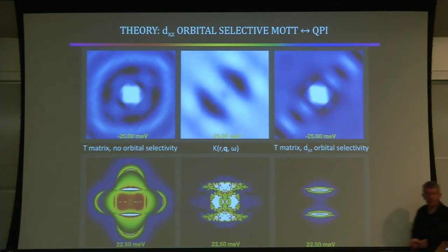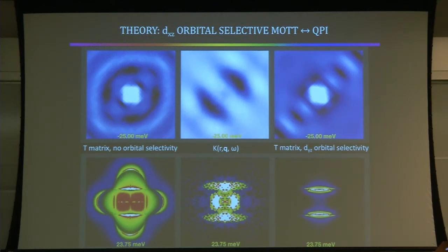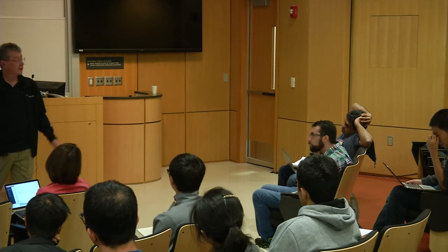So if you assume the impurity scatter... Say again? So the model for the impurities? It's a delta function in real space, so it's homogeneous in K space. The T matrix doesn't have any weights as a function of location. It's implausible that if it was an internal structure of the scatterer, that it would simultaneously produce this result and an anisotropic gap structure in momentum space for the same parameters. So we don't believe that it's a property of the scatterer. We have a good idea what the scatterer is. It's a vacancy on the iron site, so it isn't a very complicated object. It's just a delta function potential. And that would scatter between different orbitals? It will. So in our model, it's a diagonal T matrix. It does not scatter between different orbitals. That's correct.